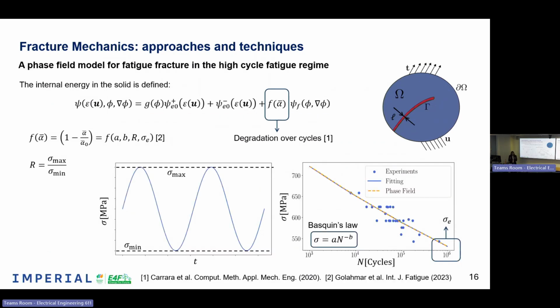So now we can also extend this to fatigue, that is the main topic, just adding a degradation function that is degrading the critical energy release rate, the material property that is defining fracture basically, over the cycles. Using this function just here in the formulation, we can apply cyclic loads. And this function, there has been many proposals for the definition, but I will tell you just one proposal that seems to be very suitable. Is a function of different terms here.